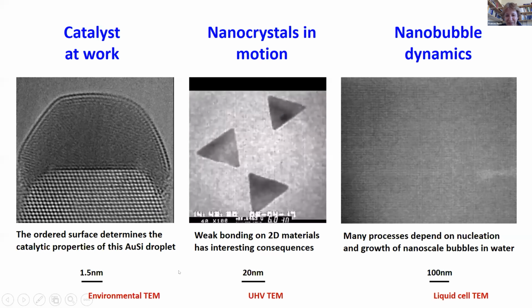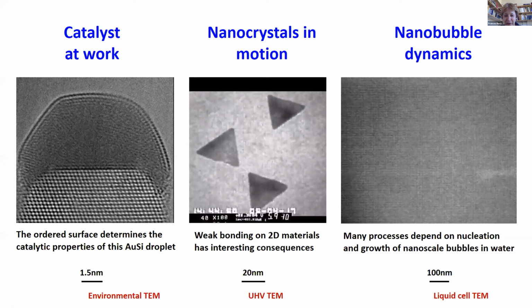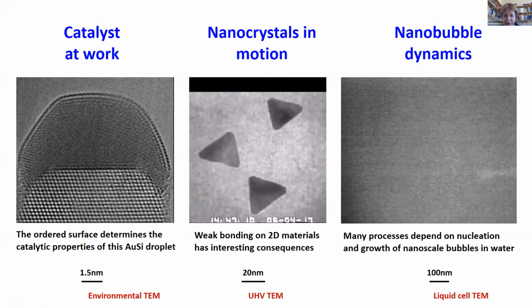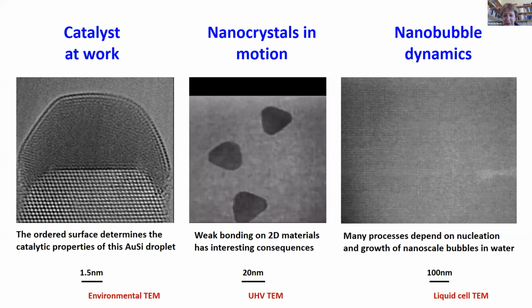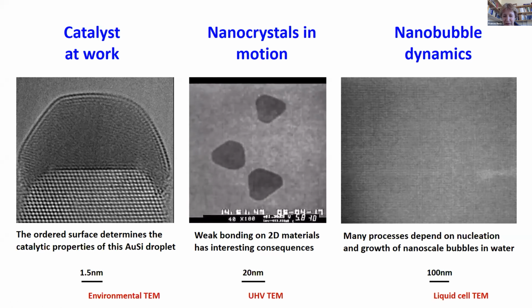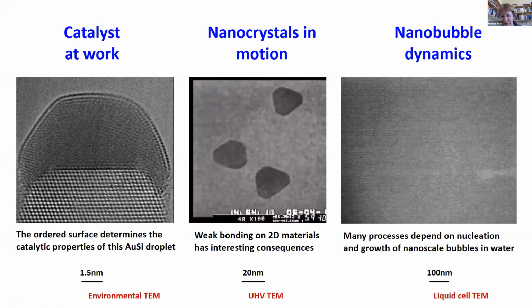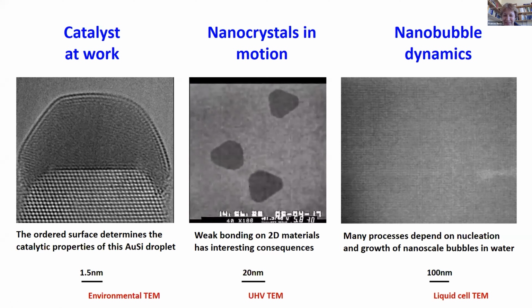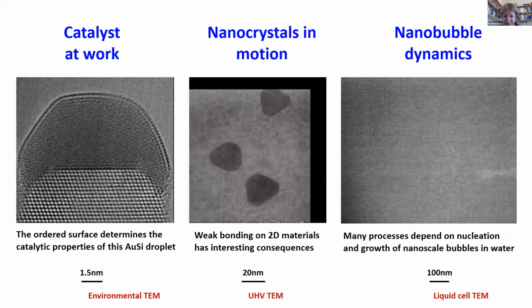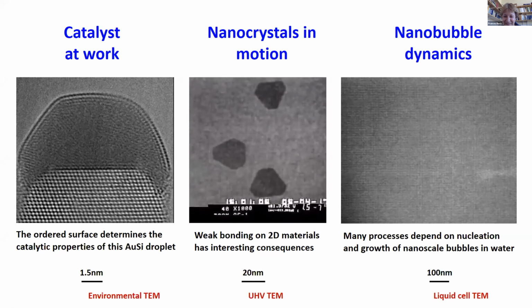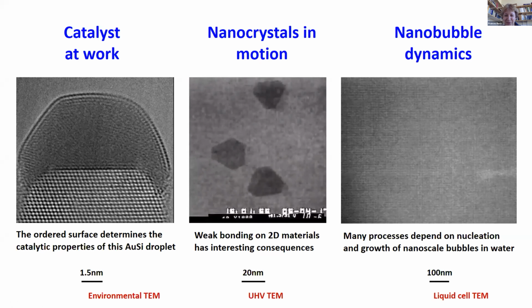Right. So in the next movie, I'm showing some gold triangles. They're resting on a sheet of graphene, and we're slowly warming them up. And what you can see is that they are moving around. I know the frame's moving too, but the particles themselves are moving. Look at the bottom one, it's going to rotate in a moment. Yes, there we go. So they're at their equilibrium Wulff shape sitting on the surface. They have very weak bonding to the graphene layer, and we'll talk about that a little bit more later on.